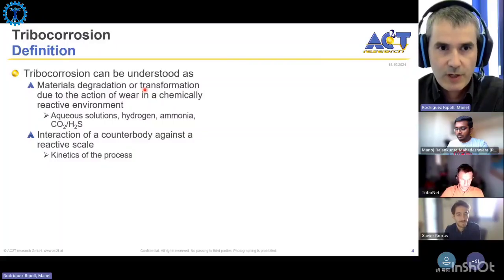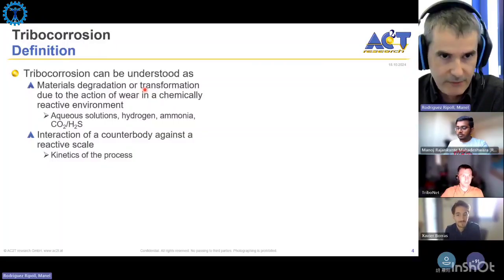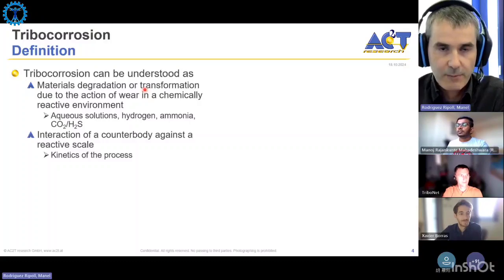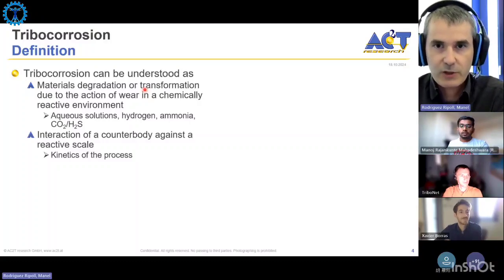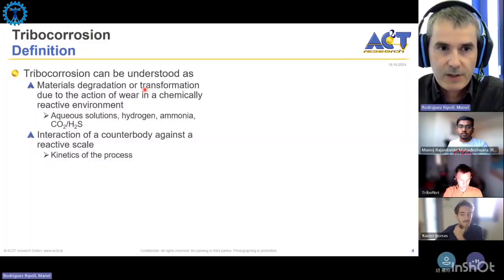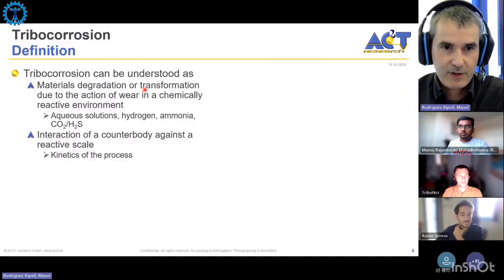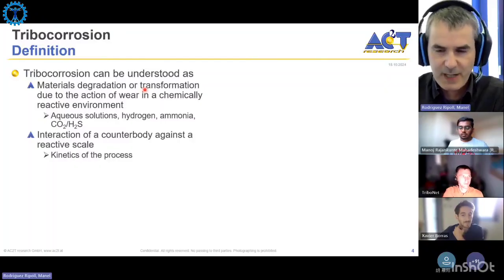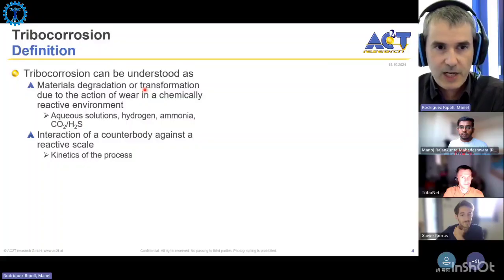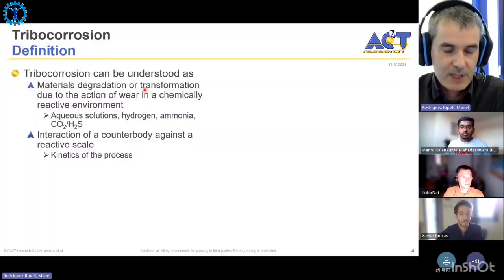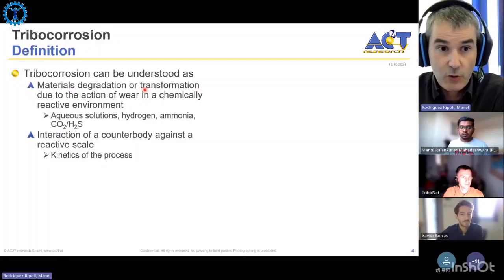In the case of tribocorrosion, the material reacts with the media, even if you don't have any mechanical wear. But when you have wear and the material simultaneously reacting with the environment, then that is what we talk about as tribocorrosion. And of course here we need to talk a bit about the kinetics of the process, because if you have a process where the wear is progressing much faster than corrosion, probably you can ignore corrosion, or vice versa. If you have a wear process that is much slower when compared to the corrosion progress, then you can ignore wear and probably you have a pure corrosion process.